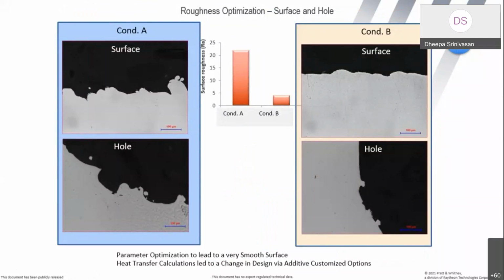What does that prescribe? All of you know the surface roughness is a big issue in additively manufactured components. Even if it is an external surface, you can add a little more and then conventionally machine that component without having a high surface roughness. It can be very low. However, you all know that surface roughness is especially a problem internal to the geometry. External, at least you can give.